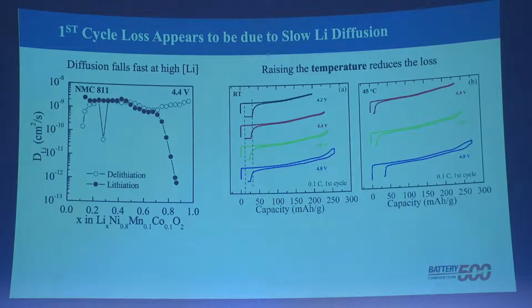We discharge to 2.8 volts. To see where there's kinetic control, we then just held it at 2.8 volts. And you can see the flat plateau, I think this bit here. If you hold it there, you're getting more and more lithium in. At 45 degrees, you're getting it essentially all back in. So this is clearly diffusion controlled.